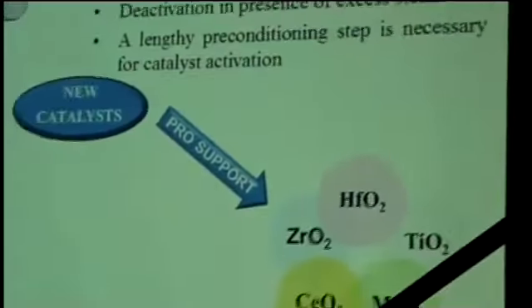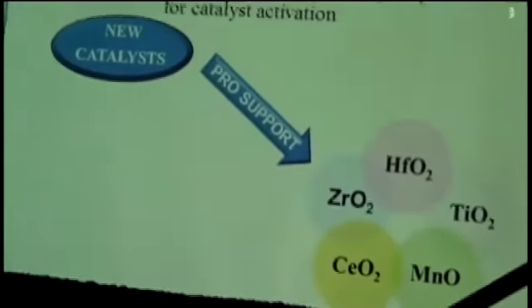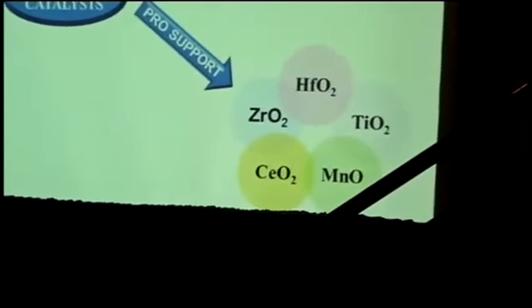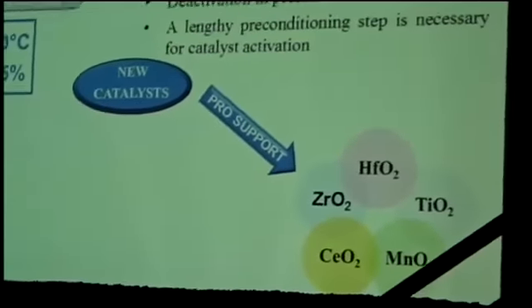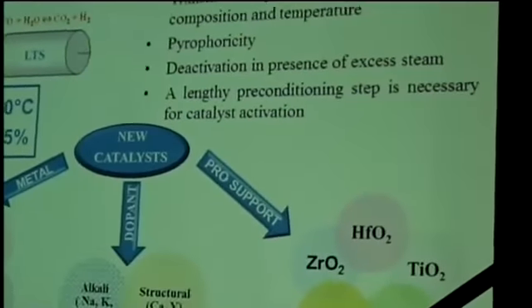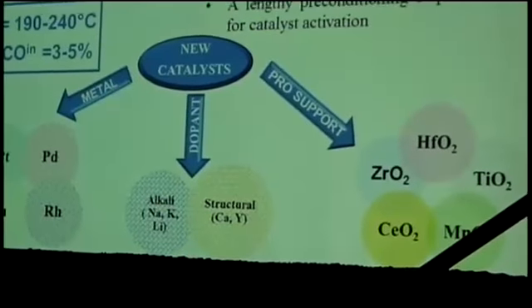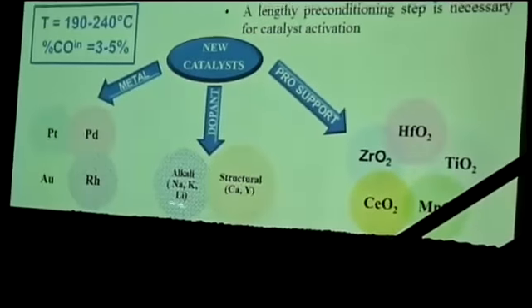So for, again, the last couple of decades, researchers have been looking into new catalysts based on partially reducible oxide. And in some cases, the reduction is really very small, confined to defects such as oxygen vacancies on the surface, as well as a small amount of precious metal, which is used to facilitate reduction and also, as I'll show, participate in the mechanism. The most recent research has been on trying to improve these catalysts, and we've had some pretty good success with doping calcia into ceria to improve its reducibility. Today we'll look at doping zirconia by yttria. And then we'll also look at another kind of dopant, electronic modifiers.